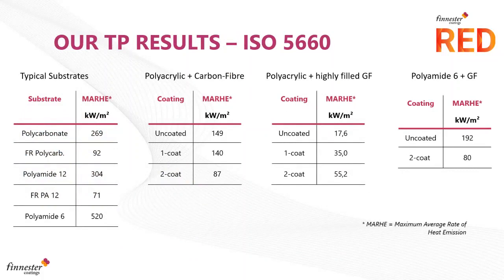A few more results here. I won't go through these in great detail. On the left-hand side, we have some typical, again, MARHE numbers, the maximum average rate of heat emission. So if you recall, we're really trying to get below 90 for it to be significant. And you can see the substrates that come in can be all sorts of numbers. They can be down to 70, but often they're in the several hundreds, as much as 500 possibly. When we're adding coatings on top of those substrates, we can bring the numbers down again. As you can see, a two-coat system can bring us into hazard level 2, perhaps, or a one-coat system. If we're already at hazard level 3, we can maintain that with a one-coat system.